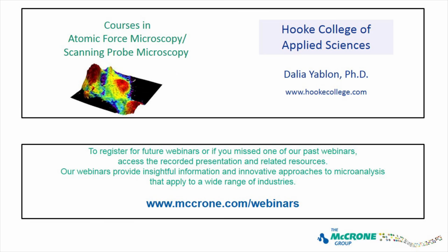A couple more questions. How quantitative is the modulus measurement off of a force curve? What is the error on that measurement? That, of course, is the $64,000 question. I can tell you that practically, in my own experience doing force curves and measurements like that for about 20 years now, your best case accuracy, meaning you put a lot of work into calibrations, a lot of statistics, a lot of repeatability studies, is 20%. Under more practical conditions, you're probably not going to do better than 50%. Of course, it depends on your sample as well.